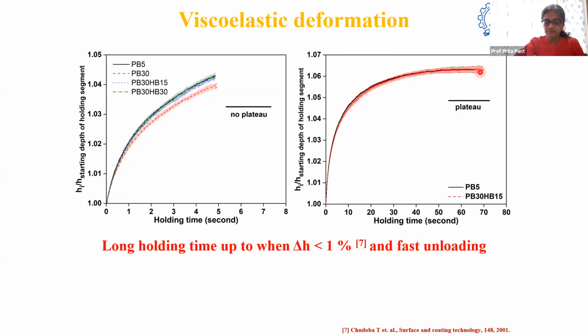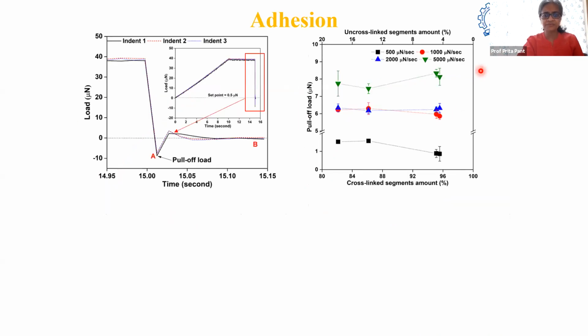So we said, okay, fine, we can give a long hold time. But again, you should be aware that if I give a long hold time, my duration of experiment goes up, and I have another limit that if I do long experiments, there is drift. So you have to take care of all of these issues. So viscoelasticity was easy. We also measured adhesion. And I think Pratyank and Asif helped us figure out how to measure adhesion.